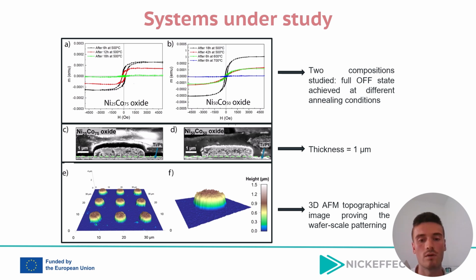To follow, cross-sectional SEM images, shown in figures C and D, reveal a consistent oxide thickness of approximately 1 micron for both compositions.